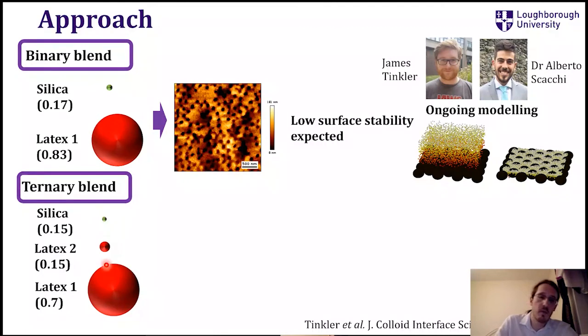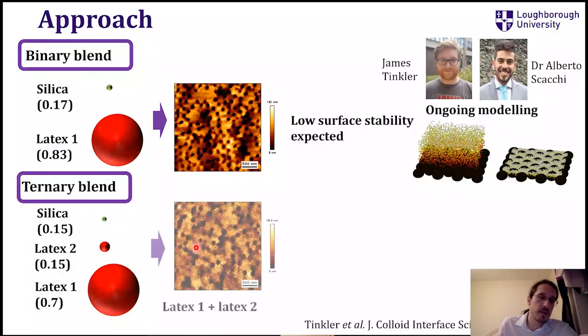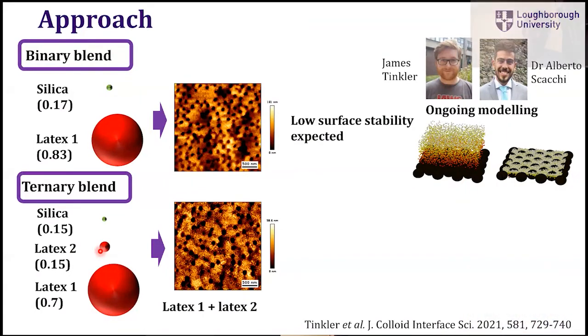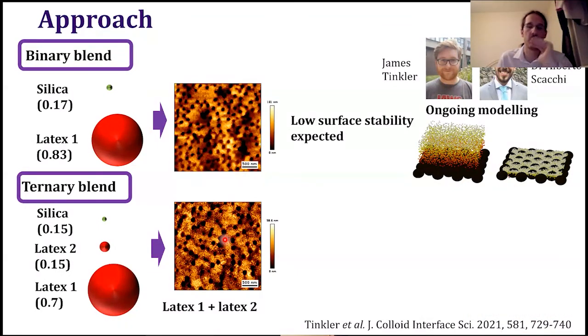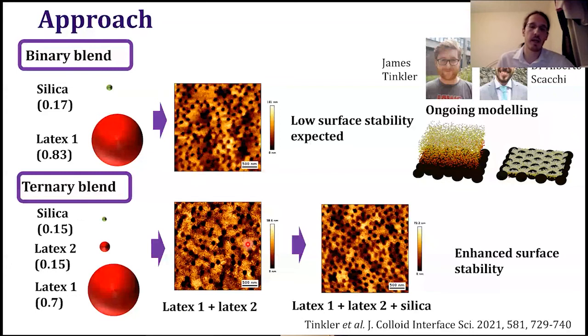If you first blend just the two latex particles, you get a similar structure, but you have the small soft particles at the top. If you add the third component, the silica goes on top of that, as we expected. So you have more or less three layers. But we're expecting that having this smaller latex particle will enhance the surface stability of the silica, and it won't be rinsed off or abraded off the surface as easily. So